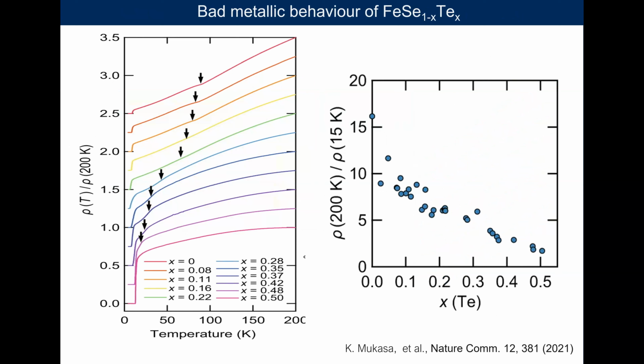So these are shifted curves, but at the bottom is adding more and more tellurium. And you can see now the resistivities are almost flat, and then suddenly superconductivity occurs. Probably this is a better representation of the ratio between high temperature and low temperature, which tells you that if the number is small, close to 1, the system barely changes with temperature. So it's a very bad metal. So on the tellurium side, the systems are quite bad metal, and resistivity highly changes with temperature before a system becomes superconducting.